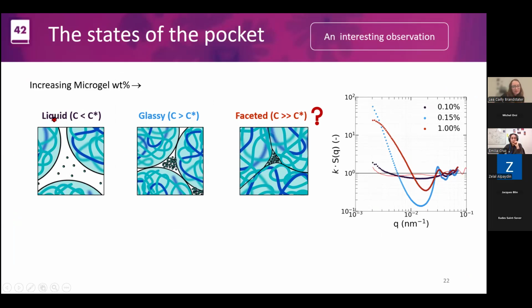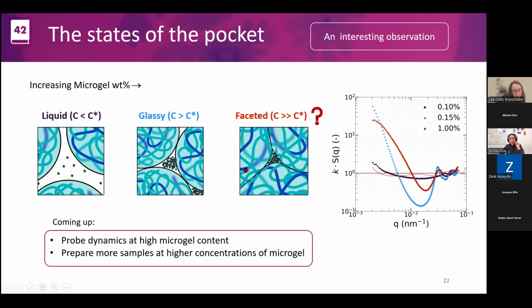But for now, just to illustrate how this would look, when you increase the microgel concentration, you go from those particles swimming to those pockets in the glassy state to perhaps a faceted scenario where you have fewer particles in a pocket. Maybe then your dispersion is a bit better for some reason, because maybe you're compressing the particles. So that would mean that the pocket is compressible, perhaps. And also, you have the probability of being next to each other at the same distance, but a bit to the right, meaning a bit closer. So coming up in future experiments, we will probe the dynamics of this kind of system to see if there's frozen dynamics, where these particles cannot move, and whether we have indeed compressed the pocket.